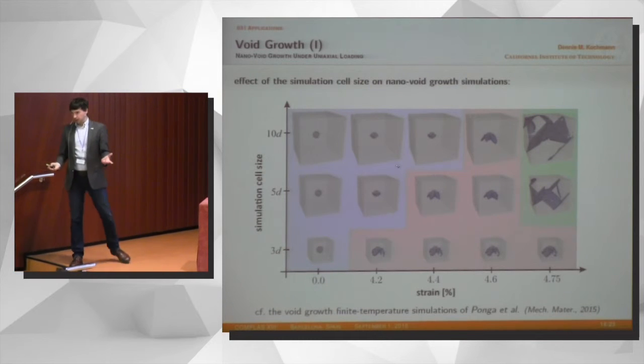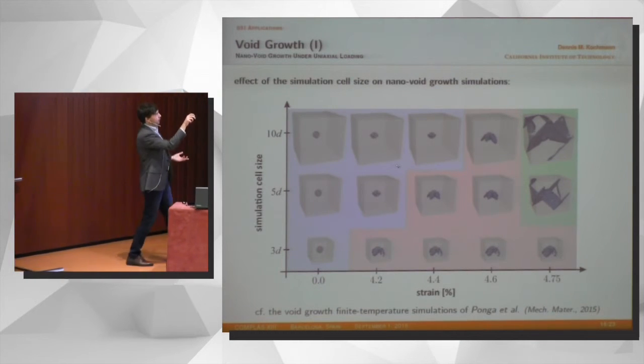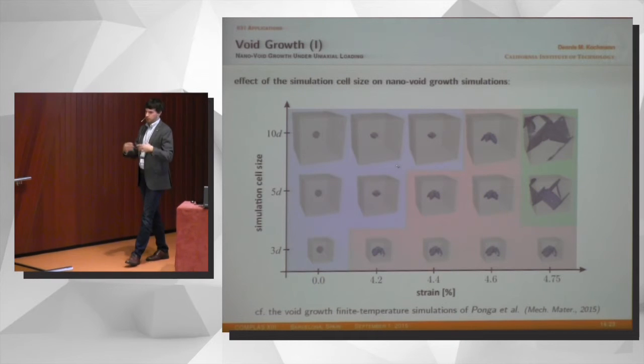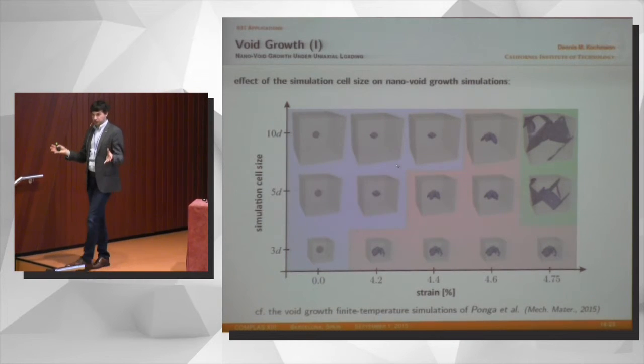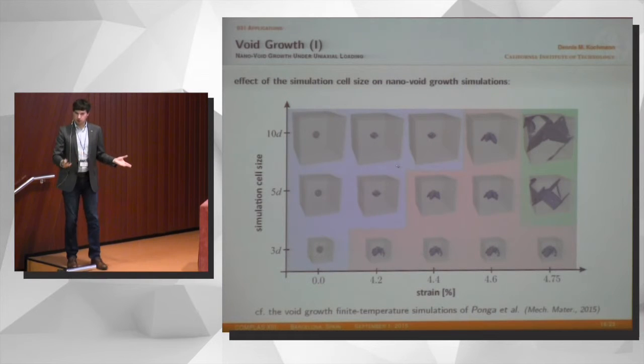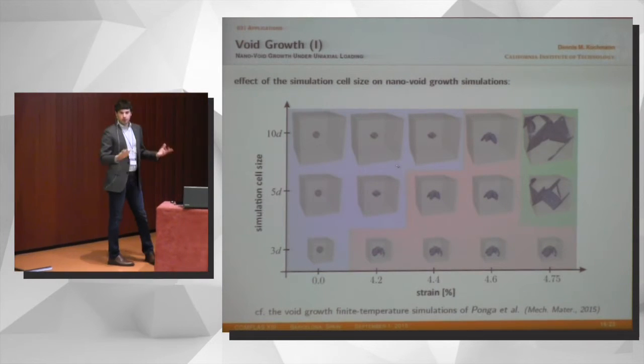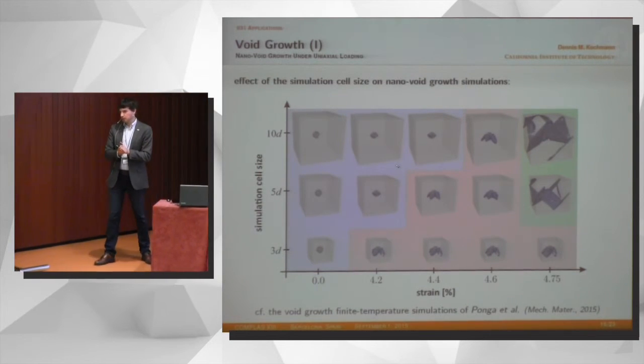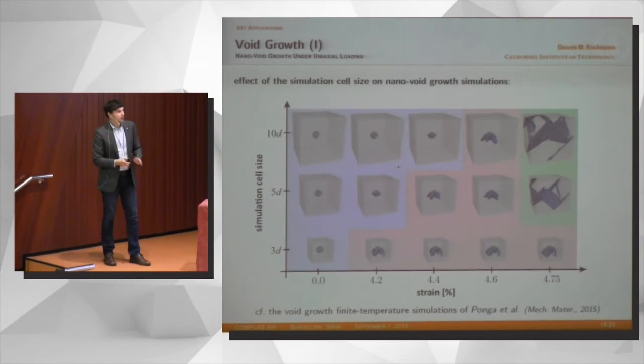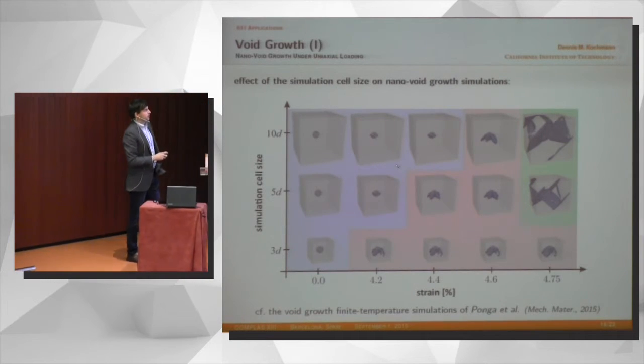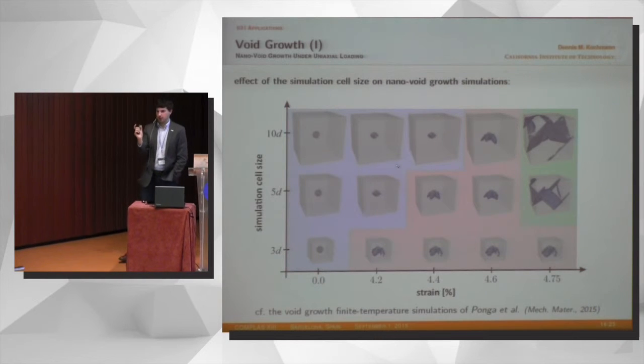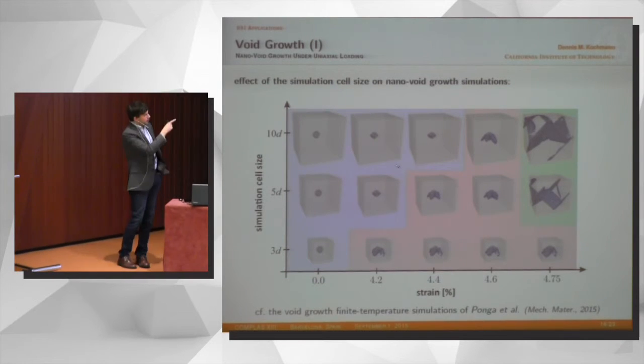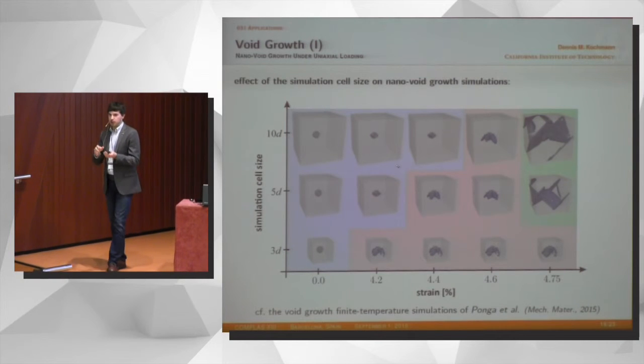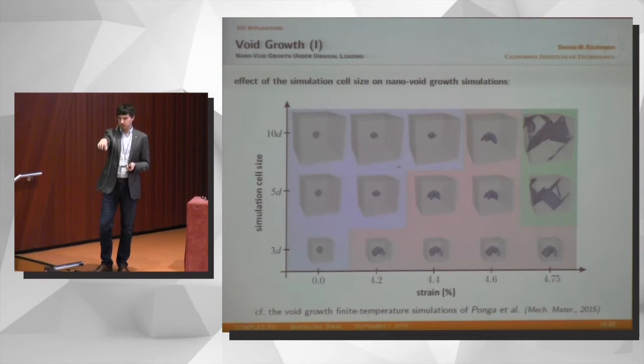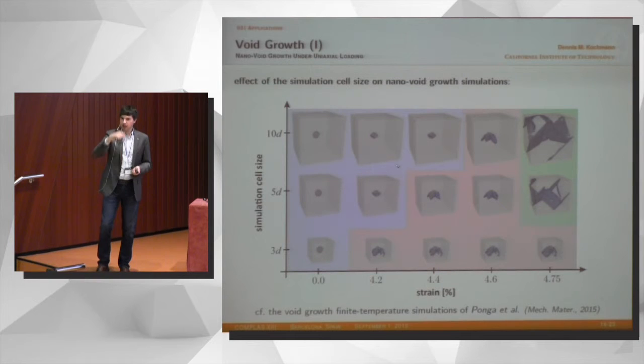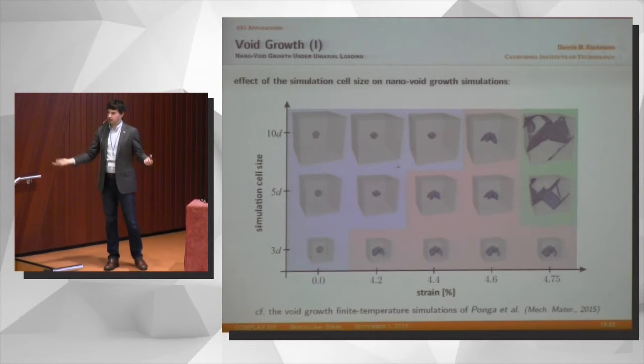Now, what boundary conditions do you apply? You could apply affine boundary conditions. That means we know the response is going to be too stiff. You could apply traction boundary conditions. That means we know it's going to be too soft. So what people normally do is use periodic boundary conditions as an optimum somewhere in the middle, as a compromise. The problem with periodic boundary conditions is that you have to be very careful about the size of the cell that you're using, because ultimately, if your cell is too small, you don't really simulate an individual void or defect, but you're simulating a periodic array of voids, and each void feels its neighbors.